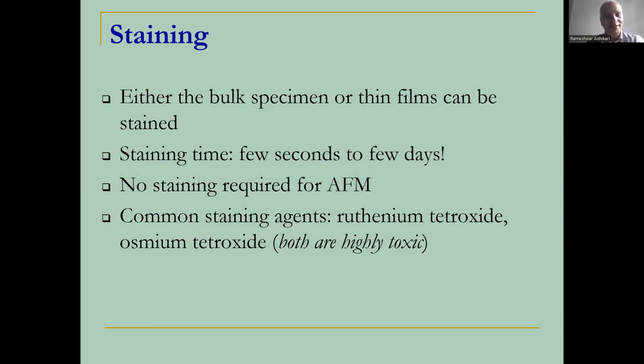And the next thing is that either the bulk specimen or the thin film can be stained, because staining is important. If we have a polymer, for example, polypropylene, what do we have in polypropylene? We have carbon and hydrogen. In polyethylene, also carbon and hydrogen. So if you have a mixture of polyethylene and polypropylene, you have only carbon and hydrogen. And these are very low atomic number, low atomic mass elements, no contrast.